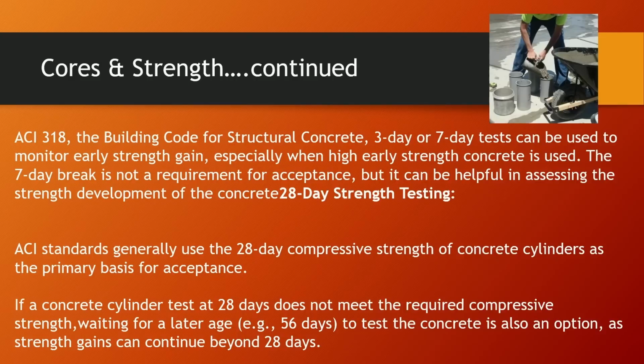28-day strength test. More and more I'm seeing everybody, we're very anxious, right? If you're pouring a slab especially, you want to get on that slab and they want to build, they want to go. So typically the rule of thumb is 70% of the strength at an early break. Most end users will let you go. So a 3 or a 7-day break is pretty important when your schedule dictates, which in today's day and age means almost always. And that's why we do it, right? It lets everybody get on the concrete faster.